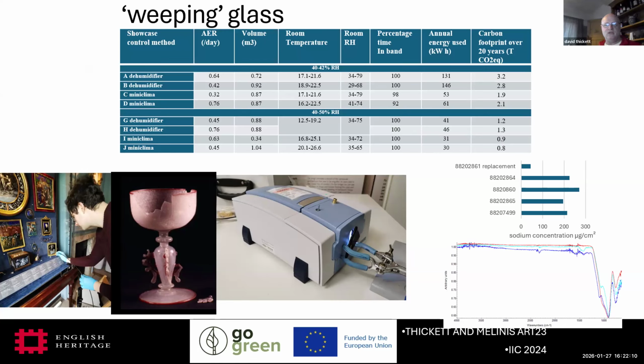And we've been doing a bit of work looking at actually about 8 methods to see if we can pick out the unstable material before it starts getting anywhere near this state and apply the preventive conservation to it. We've looked at near infrared spectroscopy, which the Smithsonian's published, FTIR spectroscopy. But the technique we found the best is to actually just swab the surface and look at the concentration of sodium or potassium ions that have come to the surface from the degradation of the glass. And this can be very sensitive.